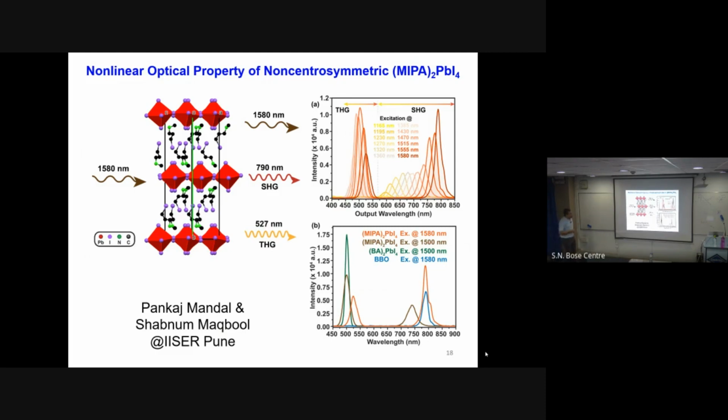And those are pretty cool. Those are 527 nanometer. This is third harmonic generation. If you look at the nonlinear optical properties, you will see things like second harmonic generation, third harmonic generation, multiple harmonic generations that are very much there. So if you shine with lambda, you'll get lambda by 2, lambda by 3, if the sample has that strong nonlinear cross-section.